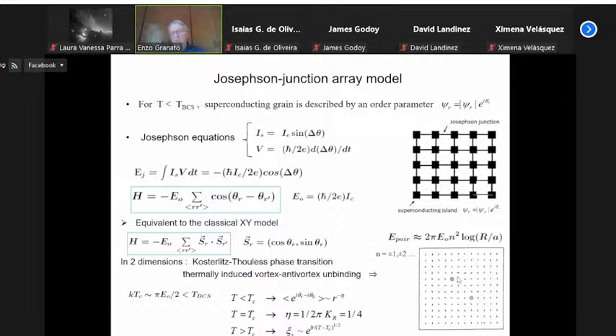This transition, in the language of the superconducting arrays, corresponds to vortices in the supercurrent, because since the current between the grains is given by the sine of the phase difference, the difference of the phases here leads to a current that circulates around the core of the vortices. So in one direction, the other direction. So the phase transition here corresponds to this unbinding of vortices of a supercurrent which circulates around the grain.